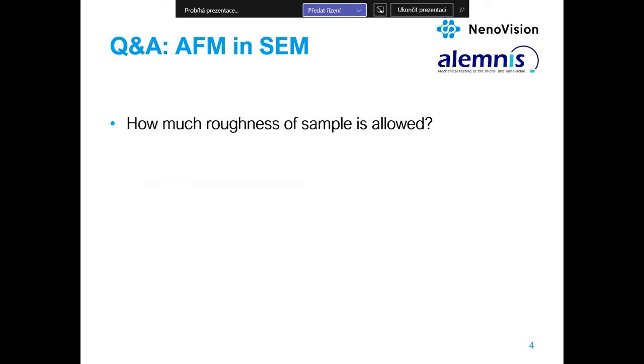Maybe I can add to that, Veronica. Typically, when we're doing nanoindentation, the ISO standard says that the surface roughness should be less than 10% of the indentation depth. So say, for example, you want to indent to 100 nanometers depth. That means your average surface roughness should be 10 nanometers or less. So that's the usefulness of actually measuring roughness by AFM, because then we can decide how deep we go with the indentation.